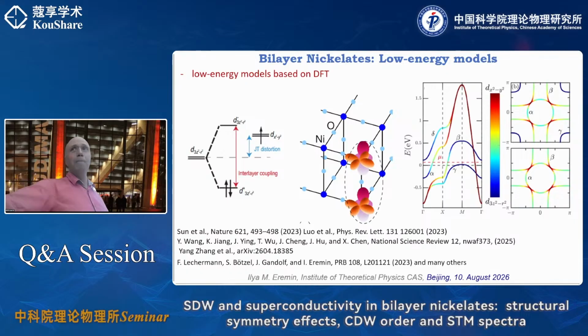Yeah, something like that. That's a problem of this two-band system: if you just have two bands, there is a condition that when you write the gap equation, which is created by the interband scattering, it requires that the gap is multiplied by the corresponding density of states. And if the density of states on the beta pocket is larger, then it has to be on the alpha. In our case, it's not the case. We only globally require that the gap changes sign between bonding and anti-bonding subspace. In principle, I think in their case the situation will change if they also allow intra-band interaction. Then of course they can change the relation between the gaps. Right.